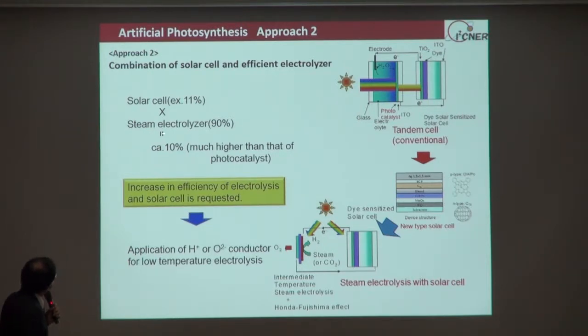And if the steam electrolyzer conversion efficiency is around 90%, then we get 10% conversion efficiency for the production of hydrogen. This is much higher than that of the photocatalyst. In addition, I also note that this targeted value is the same as that of the DOE's solar hydrogen conversion efficiency values. But in order to achieve this, an increase in the efficiency of the electrolysis and the solar cell is required, and this is our target.